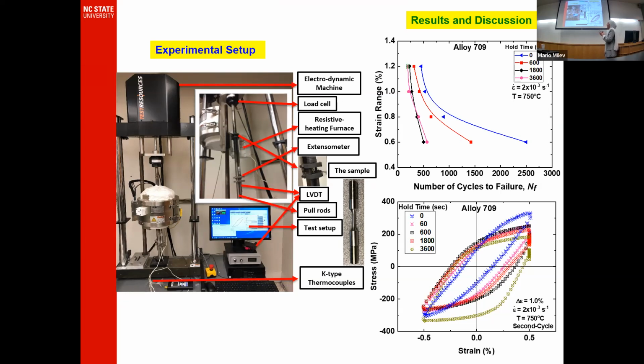And so what happens is the material fractures. Also, when we look at the hysteresis loop, we observe that when we increase the creep damage or hold time, the width of the cycle increased because of increasing inelastic strain developing in the sample itself, resulting from transformation of the elastic strain during stress relaxation.